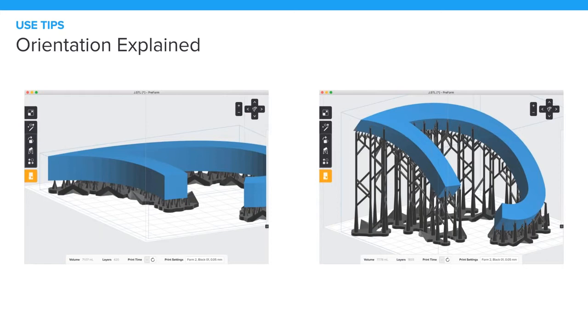So by laying the part flat, you're creating a large flat surface up against the resin tank that's going to get pulled down or yanked to the side. And so when the print is still in its very early stages, that layer may only be a half millimeter thick or less. So it's really susceptible to warping and tearing during the peel operation, especially if you have this big surface area that's only held up by these tiny little supports.